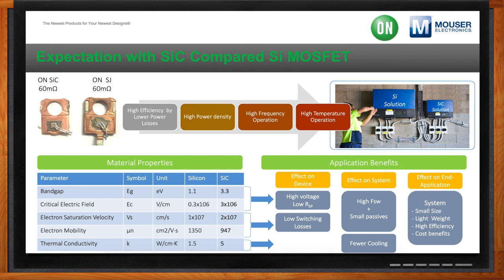So then I drop down and show you the different material properties of the silicon versus silicon carbide, and that's where we kind of get this wide band gap name from, because you can see the first parameter there, silicon has a 1.1 electron volt versus a 3.3 for SiC. And then across the board, you can see 2 to 3 times X all the parameters, including electric field, saturation velocity, mobility, and thermals. Altogether, this gives you big application benefits, including higher voltage, lower RDS(on), lower switching, which then has an effect on the system, smaller passives, less cooling.